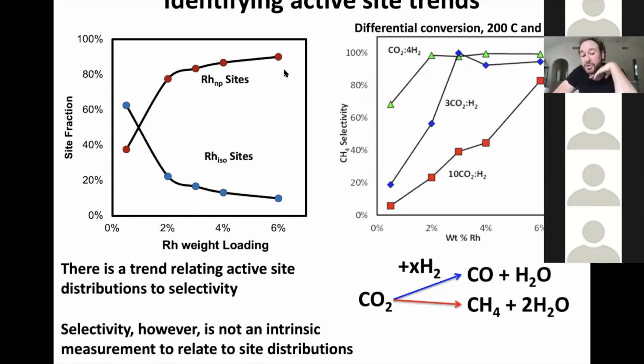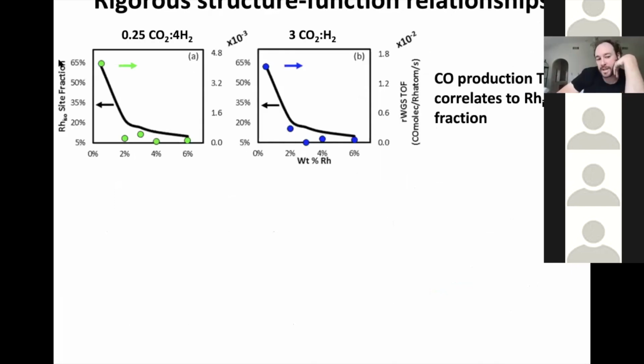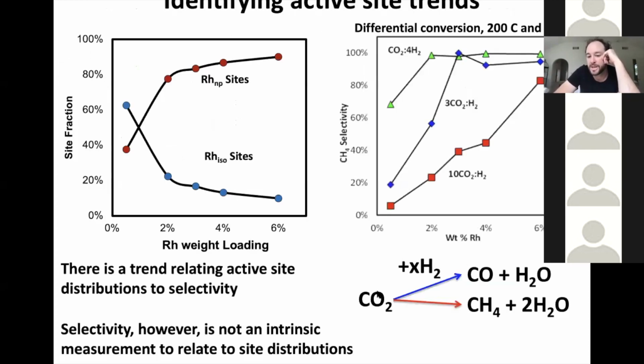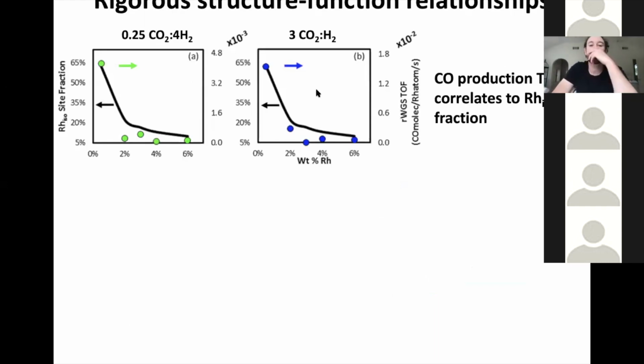However, selectivity is not an intrinsic measurement that we can relate to site distribution, so we want to decompose selectivity into turnover frequencies. So we plotted the fraction of exposed rhodium sites existing as isolated atoms as a function of weight loading, that's the black line here. Then we compared this, on this other axis, to the turnover frequency for CO production. Just to remind you, that was this pathway here. What you can see is that there was a quantitative relationship under various different conditions. We tested this under a number of different reaction conditions, and there's a direct link between the fraction of sites exposed as isolated rhodium atoms and the turnover frequency for CO production.